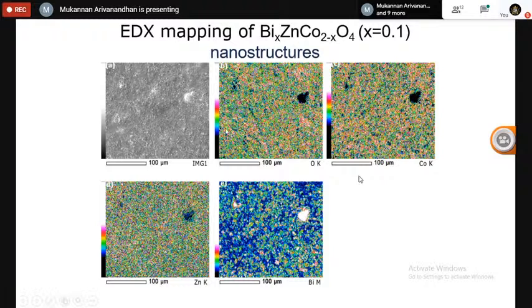Okay, so look at the mapping images. The elements are homogeneously distributed, except this bright spot. In this bright spot, the bismuth is quite rich, in addition to a reasonable amount of oxygen, which confirms the presence of bismuth oxide in the zinc cobalt oxide phase.